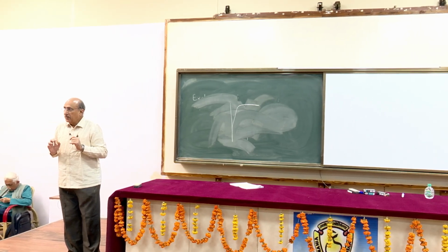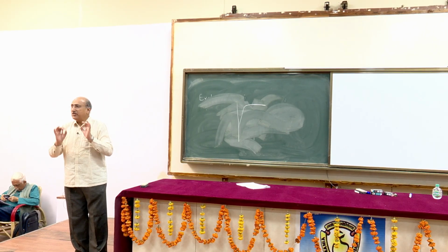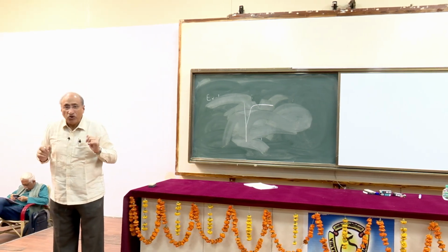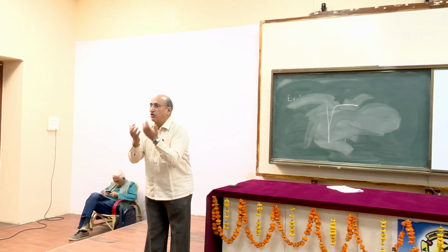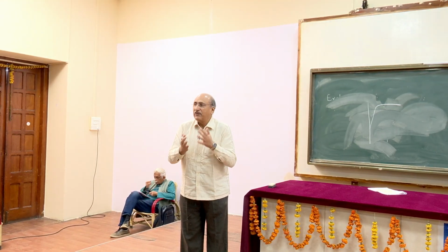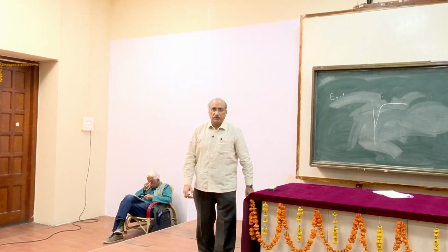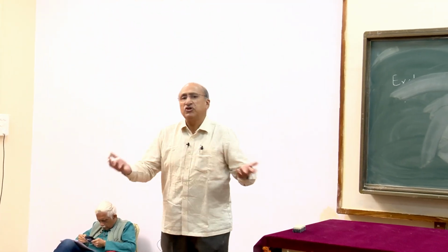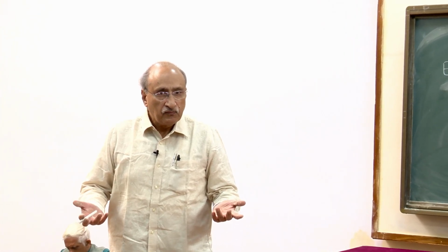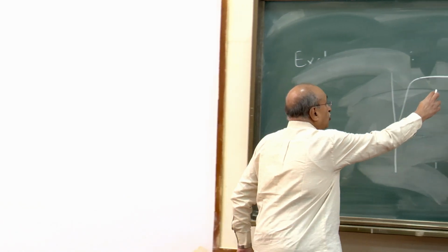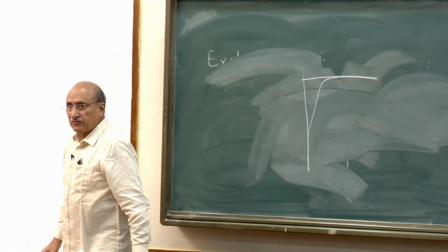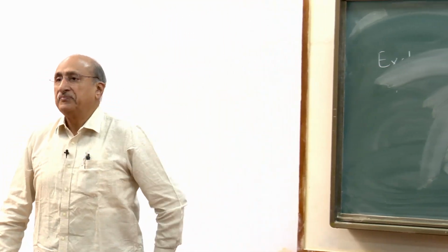All right. Now this is an easy direction. So all these domains have found their favorable position. Position, in quotes, essentially means this is where they would like to be. It's that direction where they like to sit. Now if I try to reduce the magnetic field, there is no reason why they should move. If I keep on reducing the magnetic field, all the domains will peacefully stay in the same direction. Remanence will be 1. Mr upon Ms will be 1.